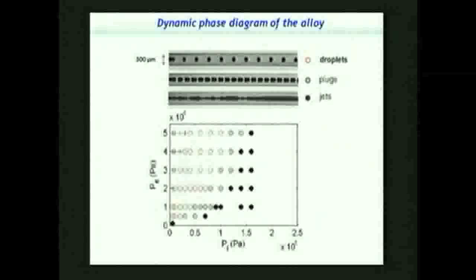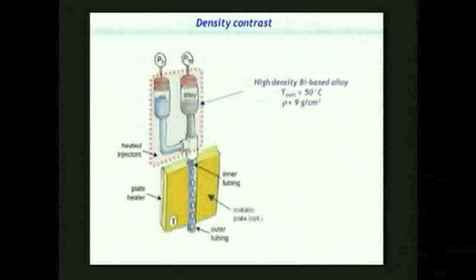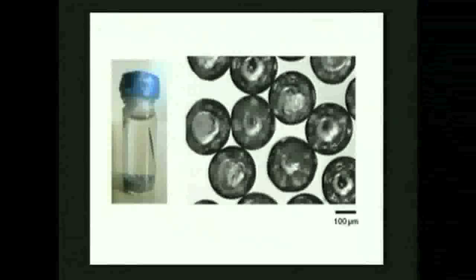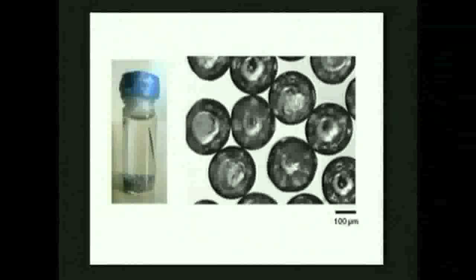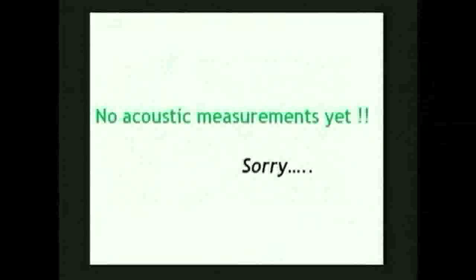And once we have chosen the right regime, it means once we are in the right regime of flow, we can decrease the temperature and go back to the solid phase of the inner particles, and this way we were able to make these very regular, spherical beads of the very dense alloy. So now we are at this stage where we try to encapsulate this alloy into an elastic shell in order to achieve the properties of the material we want to have. Okay. So I'm sorry there are no acoustic measurements yet because we have not finished to construct. This was just the idea to give you.